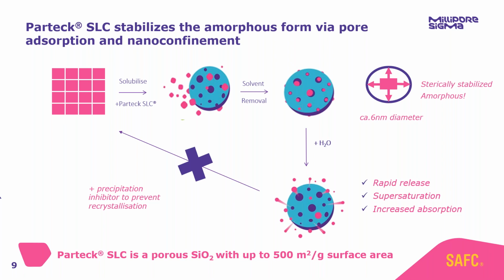And because we have the amorphous form, we generate supersaturation. So supersaturation is concentrations higher than the thermodynamic solubility. And this can ultimately increase the absorption across the gastrointestinal tract and improve the bioavailability of the molecule. The one caveat to this whole process is that as soon as you release that supersaturated API into solution, that is an unstable energetic environment. Your molecule does not want to be supersaturated.